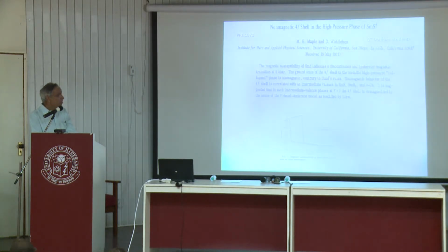Later on, people found that the properties of samarium sulfide under pressure are exactly the same as the properties of samarium hexaboride. The point here is that it looks like an average of 2 plus and 3 plus at low temperature. It neither corresponds to 2 plus nor to 3 plus. The system has got completely demagnetized. It is supposed to be magnetic, but it has completely lost its magnetism at low temperature. That was a big puzzle.